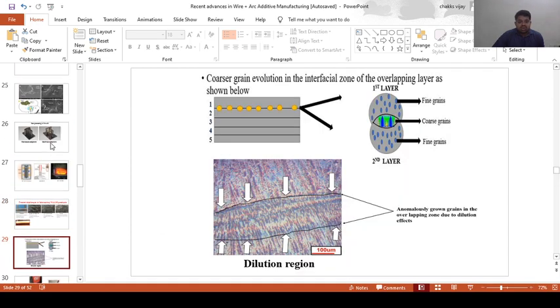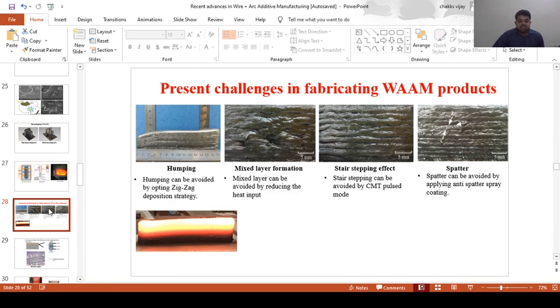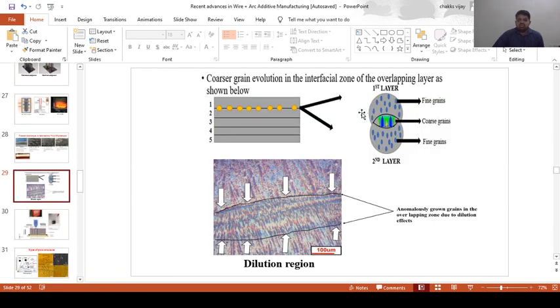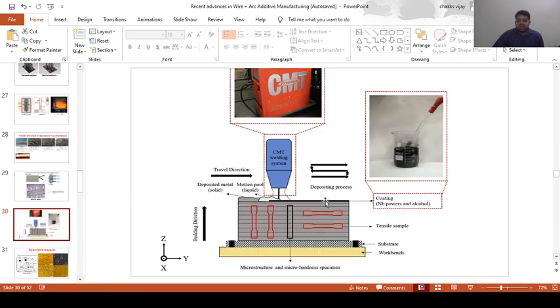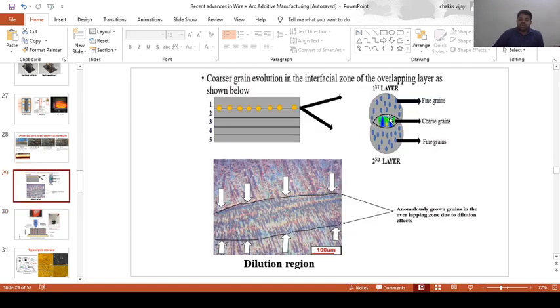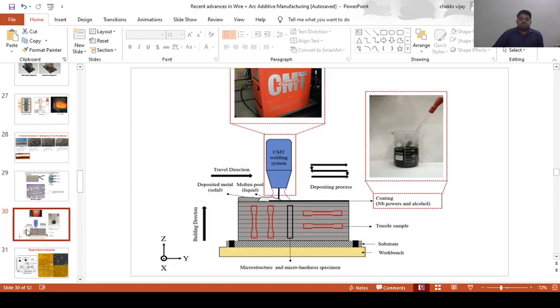I will show you that. Either we can go for a rolling operation, or else we can go for a small coating of materials like niobium, or we can use a grain refiner such as titanium. Even such powders could be coated by means of a paintbrush or something else at the end of each layer deposition, so that this grain coarsening could be greatly avoided in the dilution zone. Titanium is a very strong grain refiner, which will increase the surface wettability and promote the solidification rates, which will catalyze that.